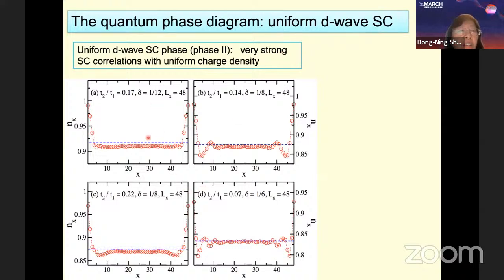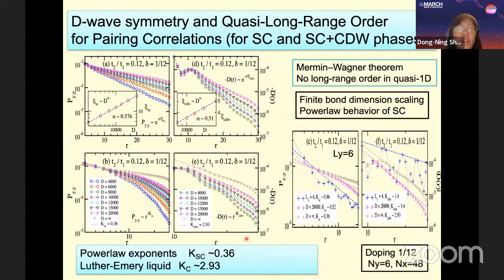Now we look at the density of the uniform D-wave phase. For different doping levels, the charge density is always very uniform. More importantly, we want to show the superconducting correlation decays as a power law. Here are examples of superconducting correlation for the uniform pairing phase.